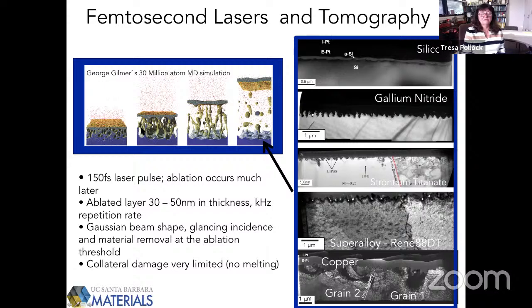And so this is just an MD simulation that gives you some sense of what that is like. So we basically deposit the radiation. In the short term, nothing but electrons interact with the system. And then in a matter of maybe nanoseconds, a liquid-like layer comes off. And because this whole process takes nanoseconds, by the time this layer is coming off the material, the beam is off. And so what that means is that you're no longer putting energy into this layer. And then what you end up with is a very low damage surface that you can directly image in the microscope. And so I show here a number of different materials after ablation.